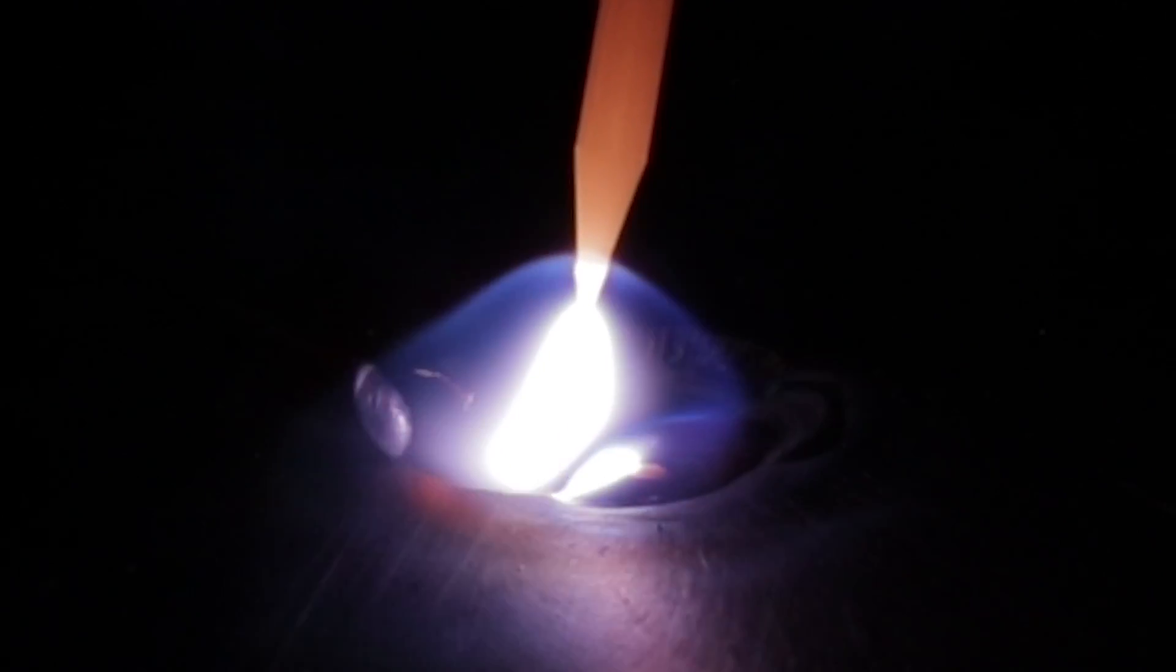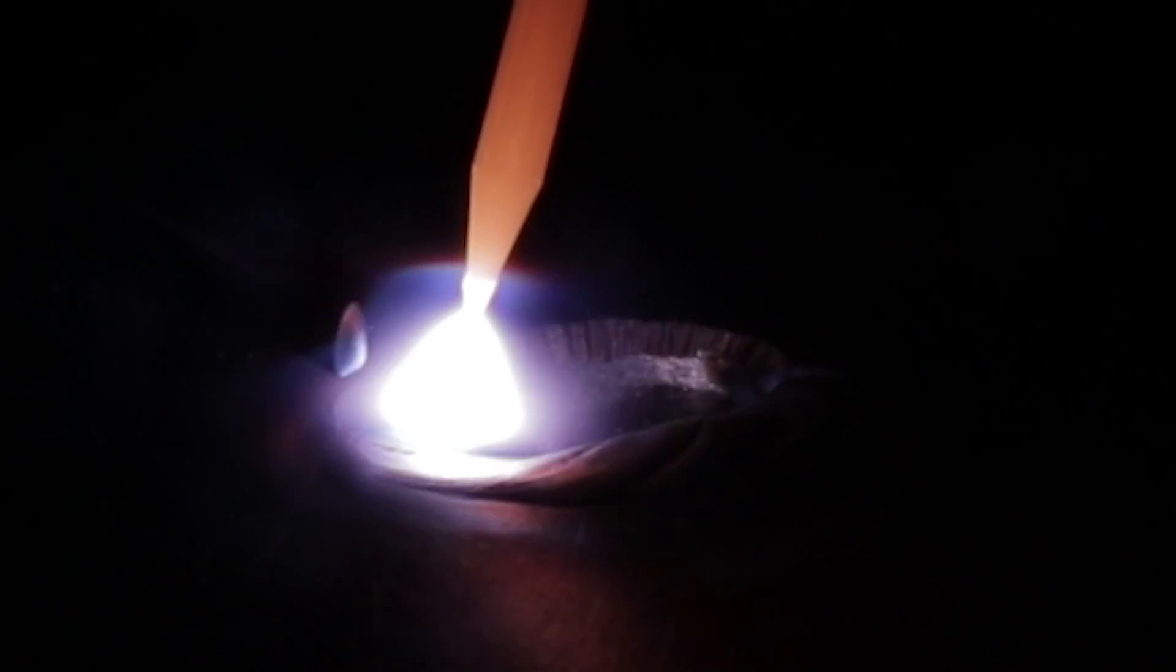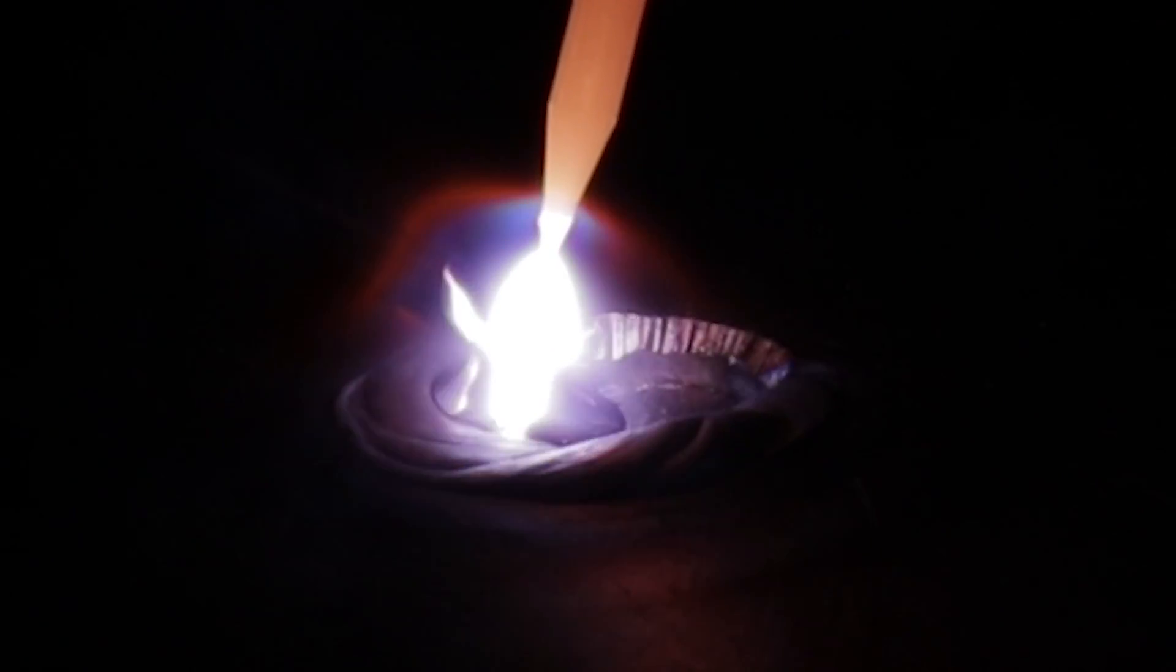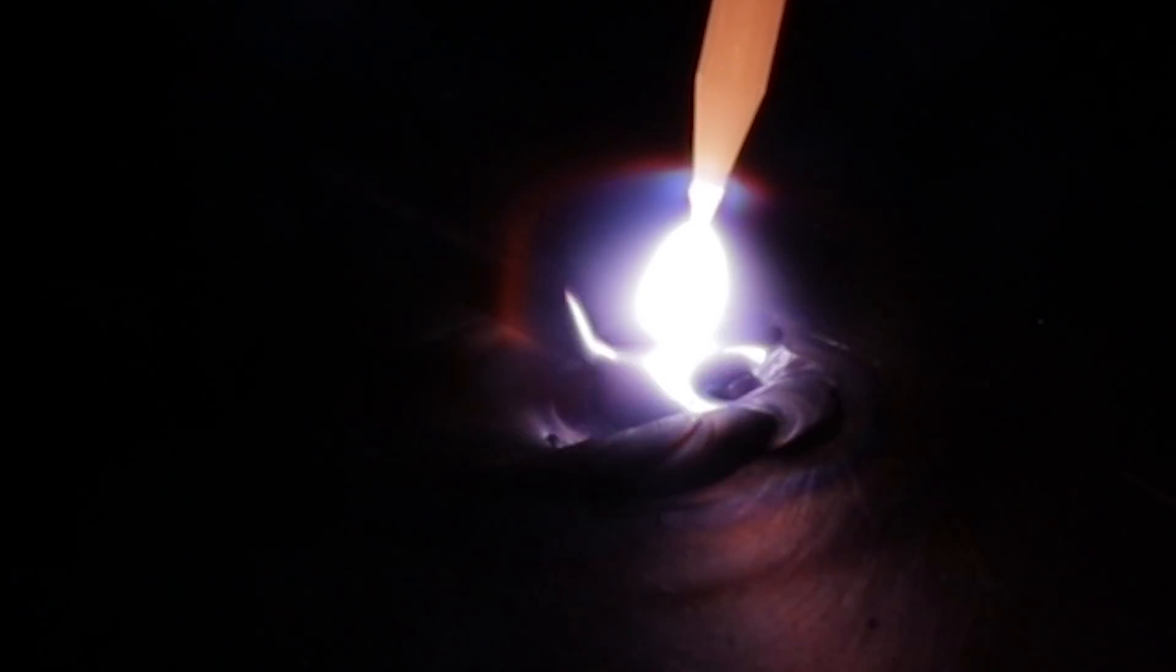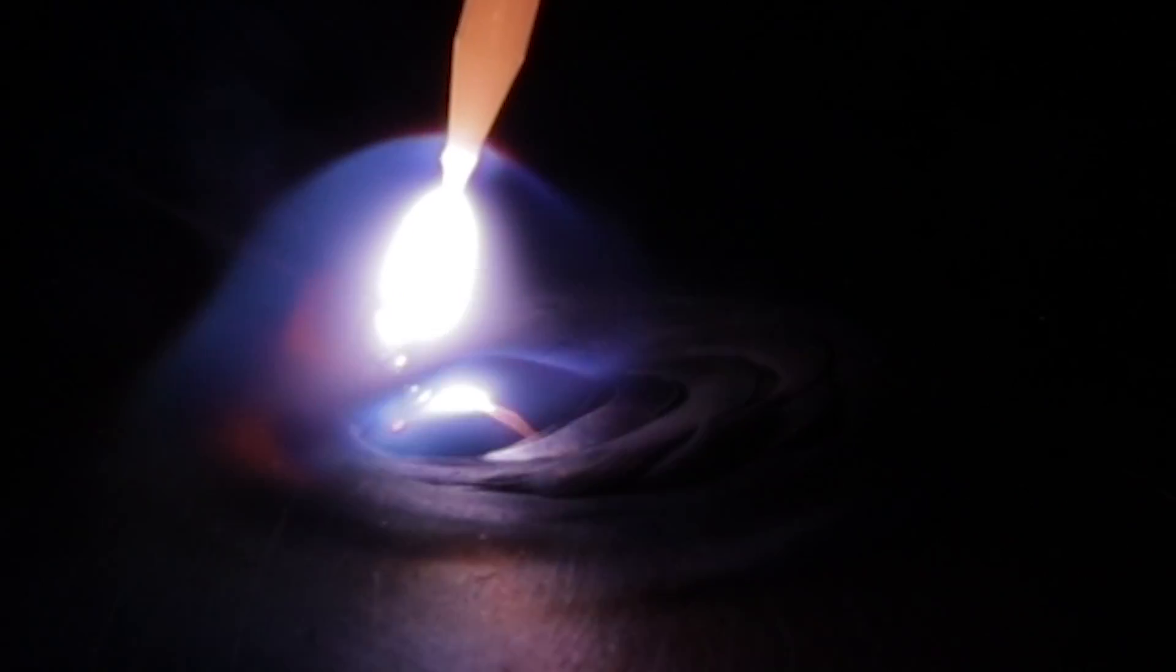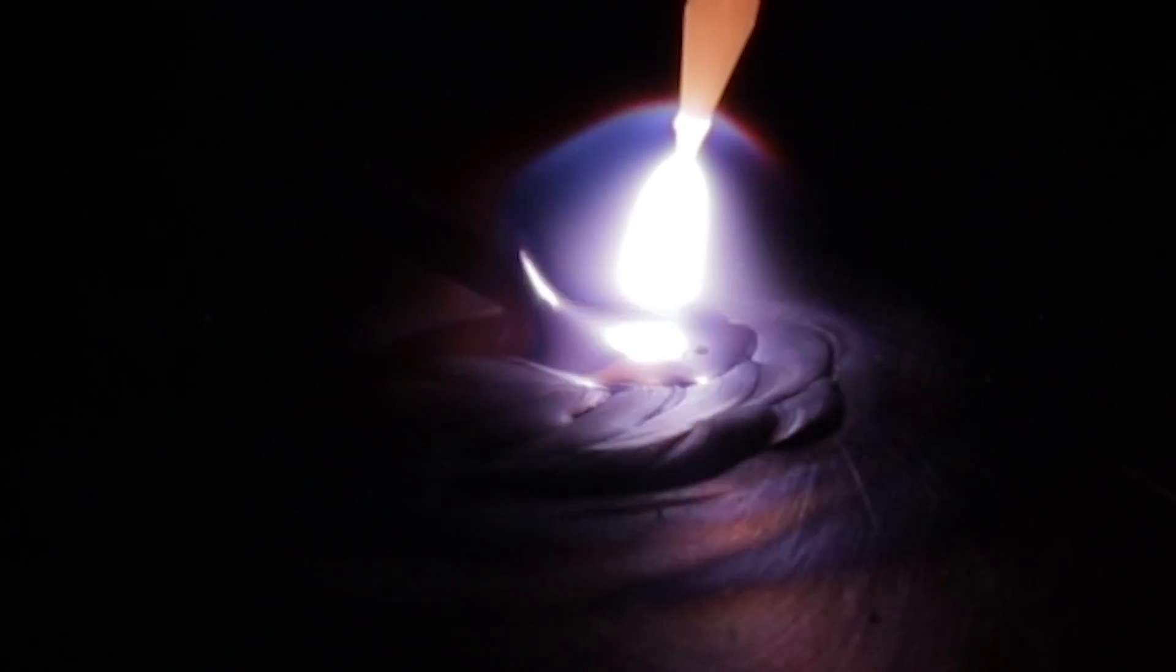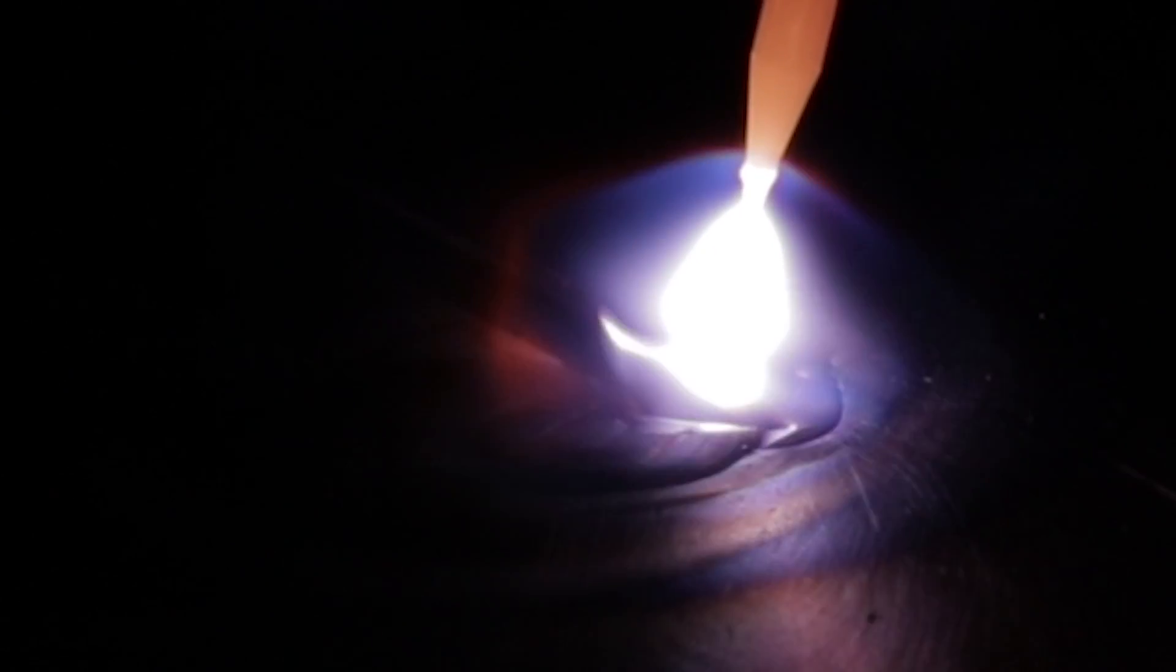And then what I'm doing is I'm going around and basically welding like a fillet or like a lap joint all the way around. And then once I get around I'll move more towards the center and fill that up and then I move over and get the edges that I haven't gotten. And once I've looped all the way around I bring it to the center and fill that up and taper off.